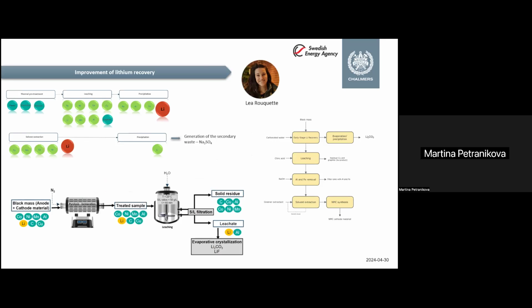So the first idea was to get the lithium first, and the main reason was that if we remember the directive, the requirement on the recovery of lithium is quite high and is going to be increased. And usually what you don't see and don't hear is that there is a loss of lithium throughout this traditional way of recycling. Some lithium is lost in the precipitation of the impurities and then also in the solvent extraction.